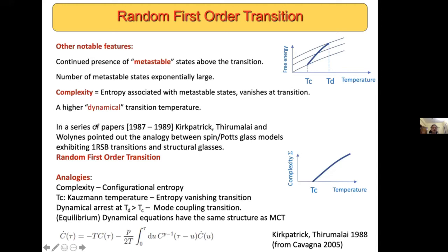this was indeed noted in a series of papers by Kirkpatrick, Thirumalai, and Wolynes in different combinations. They wrote several papers, and they pointed out that there was a strong analogy between spin or Potts glass models exhibiting 1 RSB transitions and structural glasses. And this, in subsequent literature, has come to be known as the random first order transition. So the analogy here is that the complexity is what I have earlier called the configurational entropy. The Tc is to be associated with the Kauzmann temperature, which is an entropy vanishing transition temperature. And then there is a higher temperature Td.